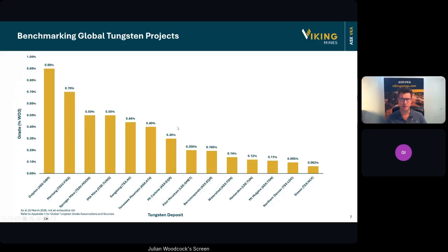What that means is we have the opportunity to reduce tonnages, which is what sits within our conceptual flow sheet, have a smaller tonnage, but which means we can have smaller infrastructure, lower capex, but we can use that higher grade and still produce a very respectable amount of concentrate in the conceptual study. So that's what we're working towards, looking at a small plant, but with higher grades, which means that we can yield comparable amounts of concentrates from peer companies that are operating on mines with much lower grades.